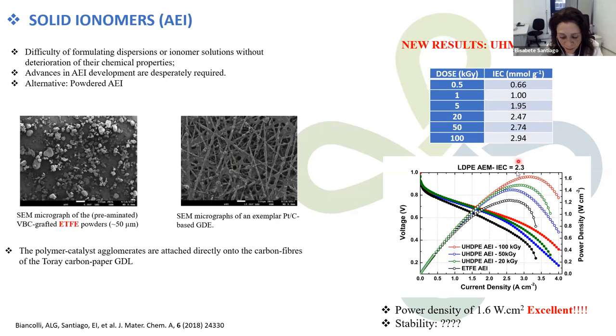So preliminary results in single fuel cells have shown that the ultra high can improve the performance of the fuel cell. You have obtained power densities of 1.6 watts per centimeter squared. This is considered very, very good, excellent. But the stability is an unknown. Now you need to know about the stability, and we have our fingers crossed that we can obtain stability for this material as well.